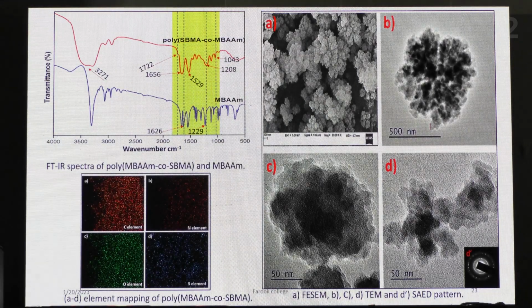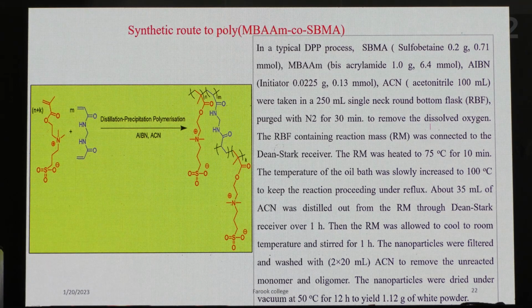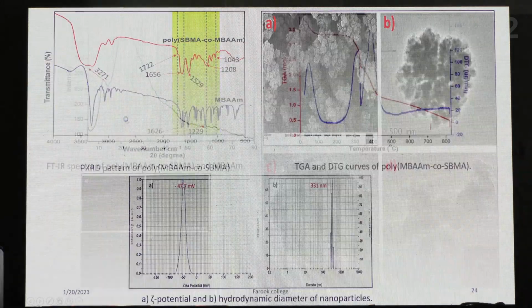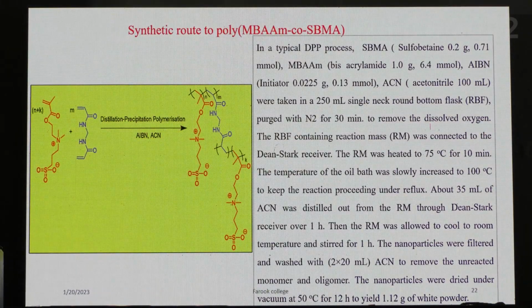And the strategy employed in this particular DPP was very simple. We have chosen two different types of monomer. One is sulfobetaine methacrylate, which we have named SBMA, and the second one is bisacrylamide, with AIBN as the initiator and acetonitrile as the solvent. With DPP, that is distillation precipitation polymerization, this is the final structure of the polymeric nanoparticle. And these nanoparticles, as I mentioned, were incorporated into the polymeric matrix as additives to the extent of about 0.2, 0.3, 0.5% in different ratios. These were purely used as additives in polymers like polysulfone as well as PVDF materials.